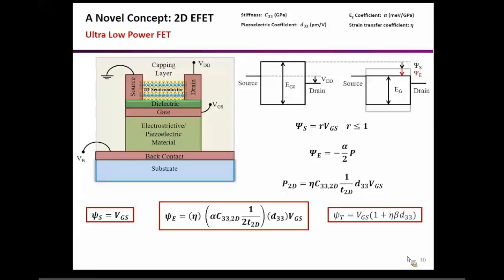So the off-state current doesn't change because in the off-state you're not applying any voltage. So I have a band gap of, let's say if I'm using a monolayer or a bilayer, 1.8 eV, which gives you a really low off current. But once you start applying the voltage, you're starting to reduce the band gap and you're going towards the on state. So your on current becomes higher. The off current still remains the same. You increase the on current and you reach the on current at a much smaller applied VGS than you will get in a conventional FET.